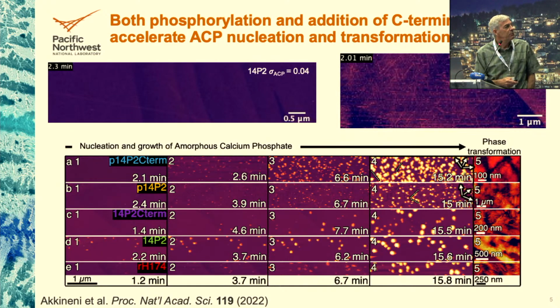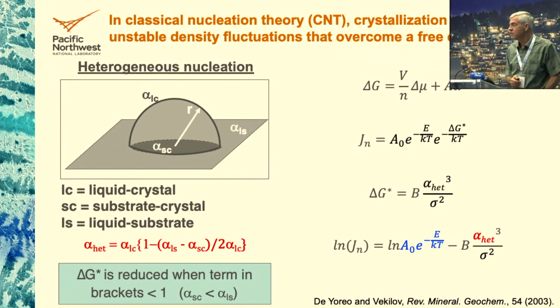Okay, so what do we do with this data? So I want to take you back to nucleation. I talked about this yesterday. So I showed you the Gibbs model for nucleation in bulk solution. And the point I want to make here is we're looking at heterogeneous nucleation, but the framework for understanding it is identical. You form a mineral particle. It has a bulk term to the free energy, which can only happen if it goes downhill and the chemical potential change is negative.